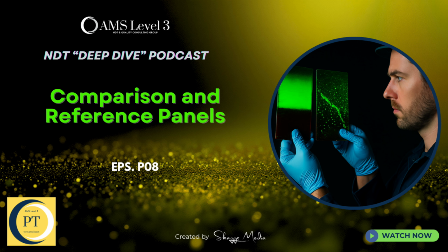And they have that groove down the middle, right? For comparing a test penetrant against a standard side by side. But didn't the source mention a problem with that? Interference. That's a big issue. Even with the groove, if the two penetrants you're comparing have very different surface tensions, they can actually creep across and affect each other. Messes up the comparison. So if you're doing a really critical test, maybe comparing performance at high temp versus room temp, you absolutely have to cut the panel physically into separate pieces.